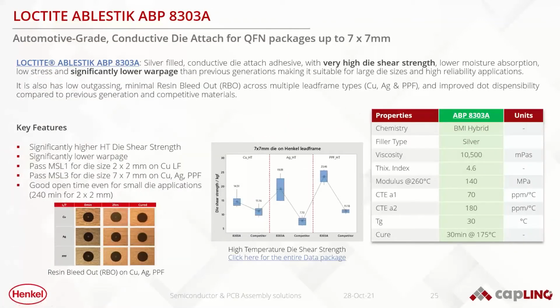The other material is the automotive grade conductive die attach for QFN packages up to 7 by 7 millimeters. This material has very high die shear strength. Compared to previous generations of our own materials, as well as competitive materials, this is really our lead push product for conductive die attach for QFN packages, especially large packages. By having a high die shear strength, low moisture absorption, and significantly lower stress and low warpage, it is more suitable for larger packages and for even higher reliability of existing packages.